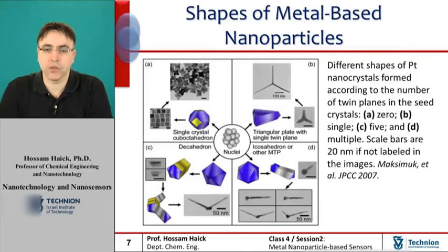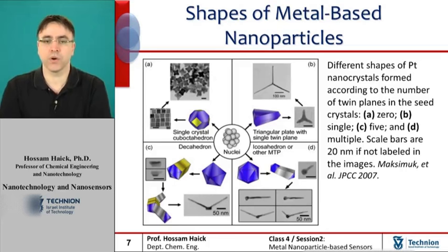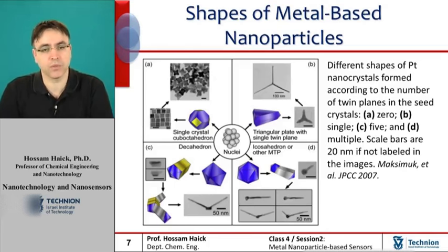Synthesis approaches are also available for controlling the shape of the nanoparticle type. Shape control is commonly achieved through a two-step process termed seed-mediated growth. In the first step of the seed-mediated growth, very small, uniform, spherical seed particles are generated. These seeds are composed of densely packed atoms with different facets and boundaries at the surface.